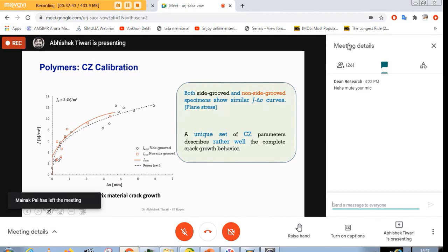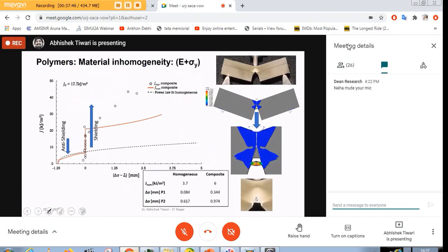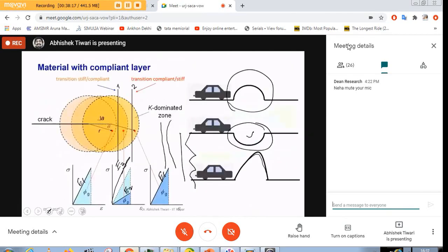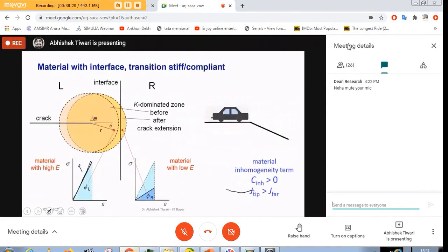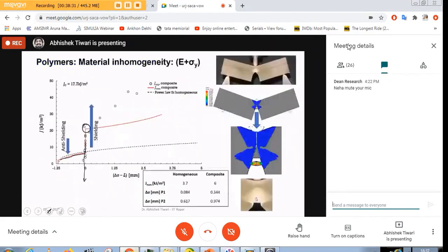Using these parameters we modeled the composite, and we could find out how much improvement in the fracture toughness can happen if we put that interlayer. Experimentally it was confirmed that the fracture toughness improved by a factor of 7. Apart from that, we also saw that the crack driving force is increasing as the crack reaches this line, which represents the interlayer. As the crack reaches the interlayer, the crack driving force increases. This is what we saw because the material is brittle. So when we go from brittle, meaning the Young's modulus is higher, to soft, the crack driving force increases, and that's what we could also see in the simulation results.